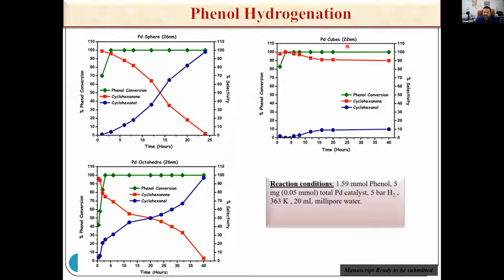Same reaction if you do on a palladium cube of 22 nanometers, you see that again the conversion reaches 100% within 2 to 3 hours, but then the selectivity is intact throughout the 40 hours period that we have run the reaction. There is only a marginal increase in cyclohexanol that is seen, probably because of the presence of some spherical particles in the supported system. But more or less what we can say is there is a huge stability for cyclohexanone when you run it on a palladium cube compared to the other two nanostructures.